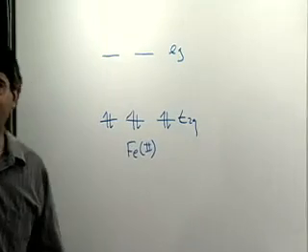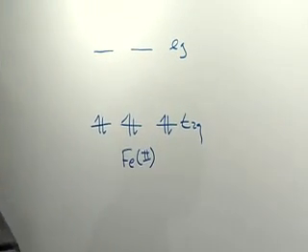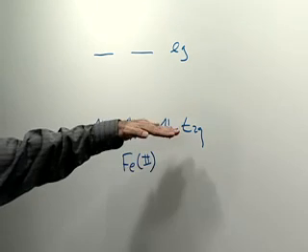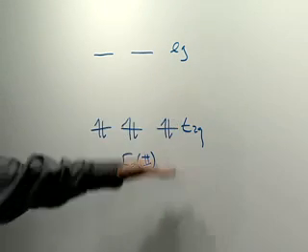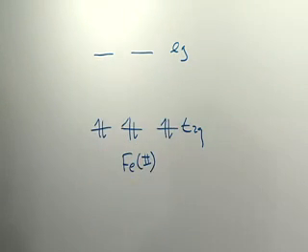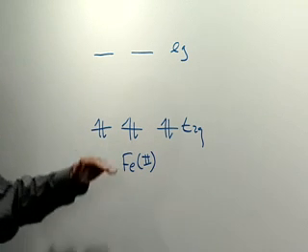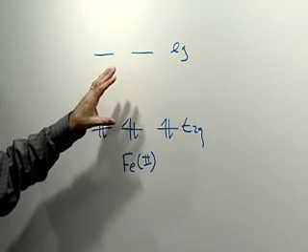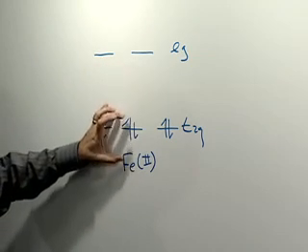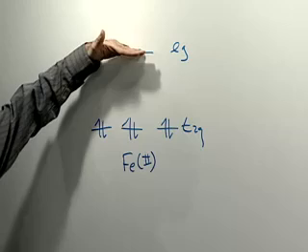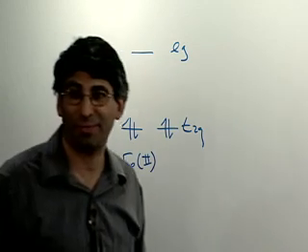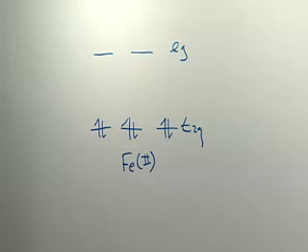It looks like that. And so all the chemistry I've been showing you has to do with removal of one of these electrons. And so if this orbital can move around as a function of the cation that's present, up or down, then I'll get a shift in the redox potential. I might, again, have seen a spectroscopic change. I didn't. I think it's because of the quality of our experiment. But in fact, it might turn out that this orbital moves up and down, and this one moves up and down also. And then spectroscopically, I don't see it, but I could still see it electrochemically. And in fact, that's what we think is happening.